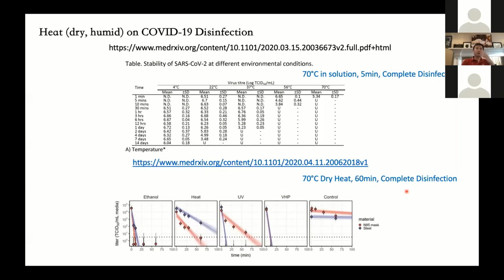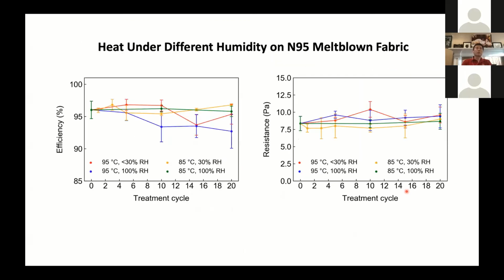So we say, this is really guiding us to be safe, to really see what temperature the facial mask can survive to maintain the filtration efficiency. We also studied 95 degrees Celsius, very humid condition, and a dry condition. And they can maintain reasonably 20 cycles of filtration efficiency. Particularly if it's dry heat, it maintains it very well. With wet heat at 95 degrees Celsius, it dropped a little bit, but still maintains about 93% filtration efficiency.